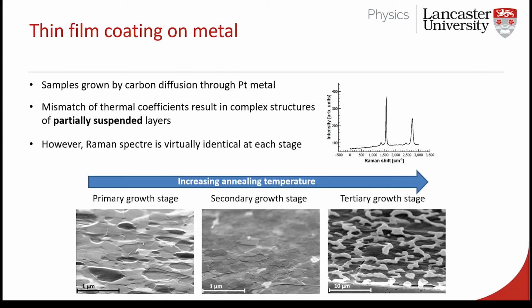And there was a big push to make graphene. And the reason it hasn't quite changed the world yet is actually to make large quantities of it is very difficult. And these collaborators of ours in France, they thought they'd cracked it. And they were growing these thin films, single atomic films, as thin as you can get of graphene on a platinum substrate. But when they looked at it under an SEM, it wasn't flat. It hadn't quite worked.